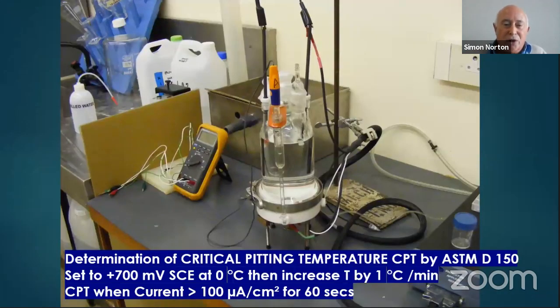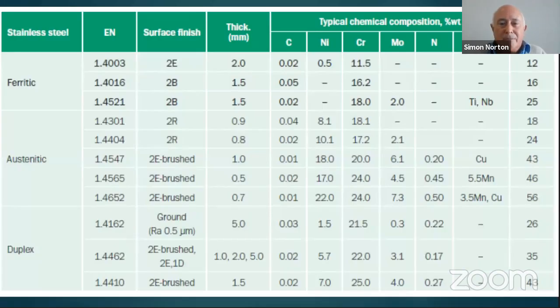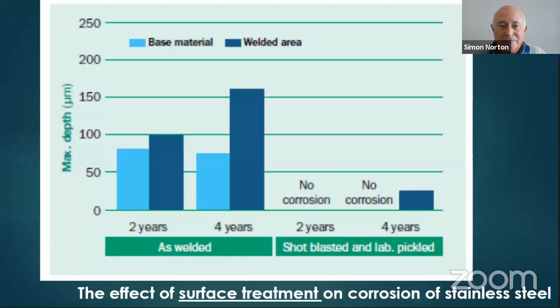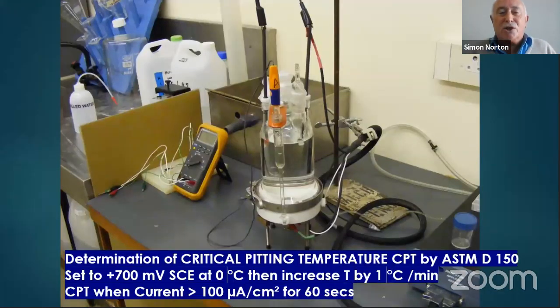Now, I referred earlier on to the PREN number, and if you look on that chart on the right-hand side, you'll see the PREN numbers for various stainless steels, and you'll see that they increase, and some of them go right up to 56. The duplex stainless steels are substantially higher than the austenitics, like 304, 1.4301, which has a PREN number of 18. 316 has a PREN number of 24. But if you look at the duplex stainless steels, they've got PREN numbers of 35 and 43, the pitting resistance equivalent number.